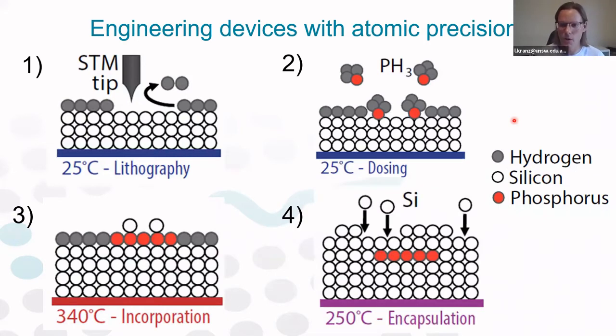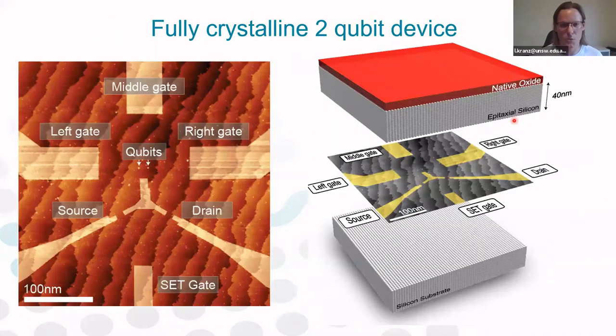And finally, we grow a protective epitaxial layer of silicon on top of that. And all of these steps are done in ultra-high vacuum. And after that, we remove the sample from the vacuum, and we use standard clean room post-processing methods to contact this buried donor device. So this here is the STM image of the device that we use for the noise measurements that I'm going to present.